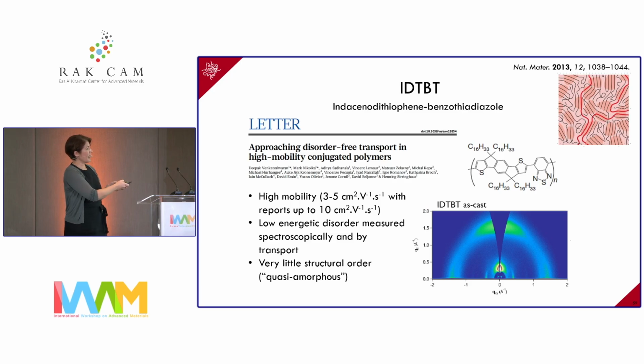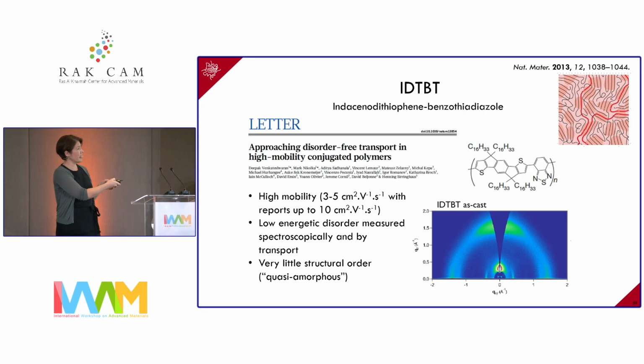It was a polymer that gave remarkably high charge mobilities, 3 to 5, but even up to 10 centimeters squared per volt second has been reported, and that's high for a polymer. But what was weird is that when you did things like X-ray or GIWAXS, there was not much structure to be seen. It was a seemingly amorphous polymer, and yet it was giving you really high charge mobilities. So going against the general design criteria that we have for these materials. So you're like, okay, this is the polymer that we're going to tackle to try and see what was happening.